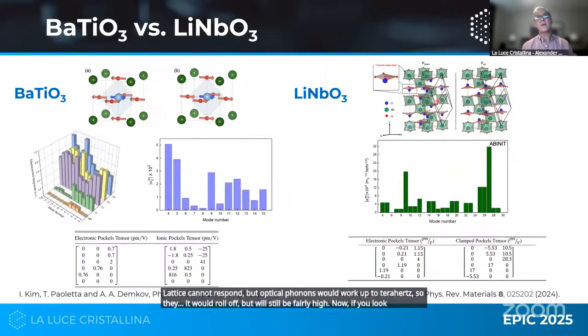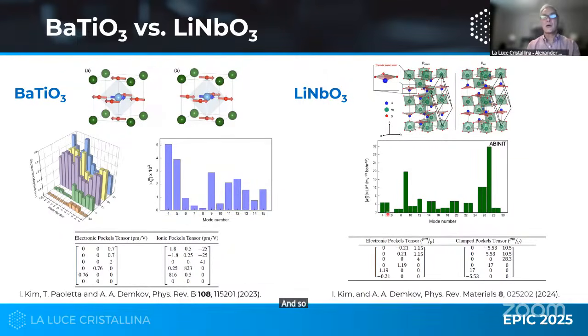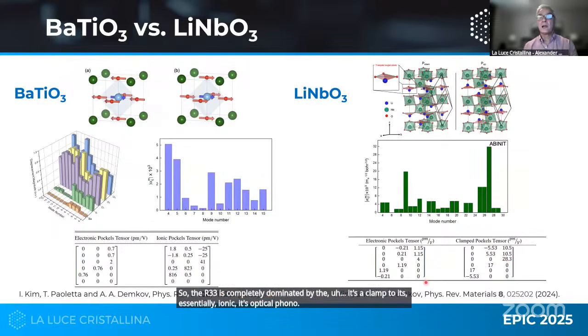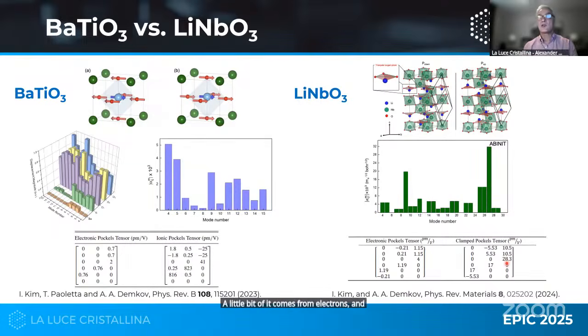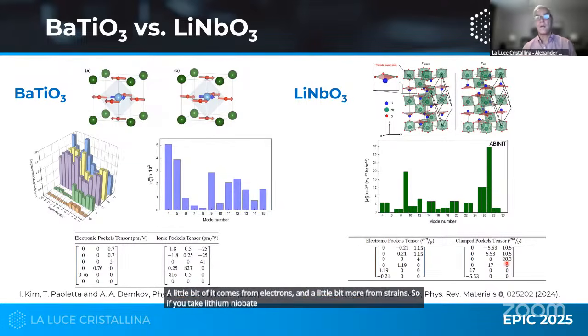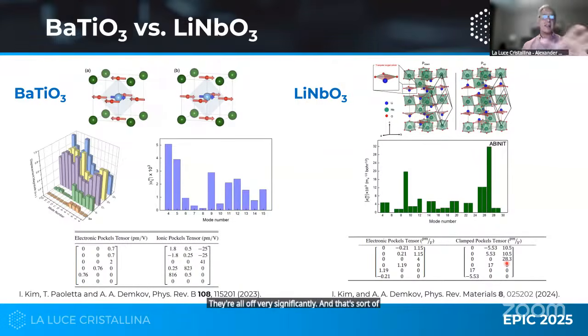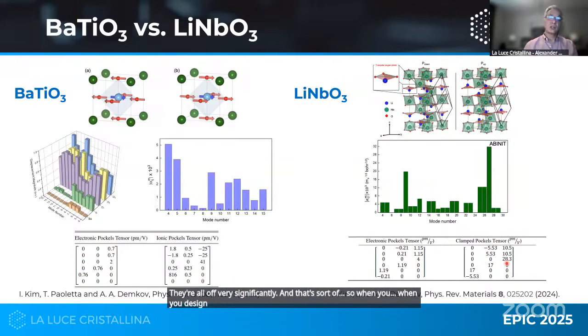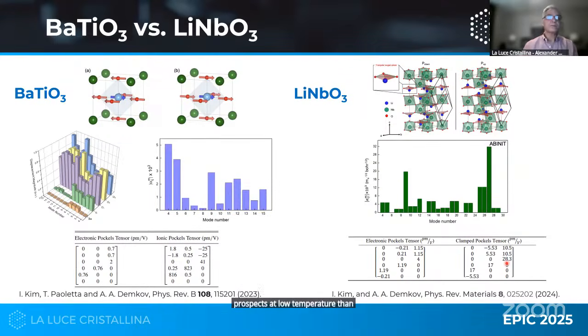Now, if you look at lithium niobate, it's a different kind of material. It's an order-disorder transition. And if you again look at the components, the R33 is completely dominated by, it's clamped, or it's essentially ionic, it's optical phonon. A little bit of it comes from electrons and a little bit more from strain. So if you take lithium niobate, it would work very well up to high frequencies, but if you go to low temperatures, it will roll off very significantly. And so when you design a structure, you have to think of the application. Barium titanate has much better prospects at low temperature than lithium niobate.